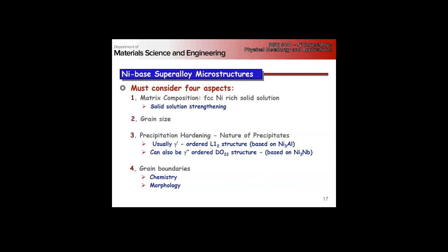When designing our superalloys, we have to think of a couple different things. Our gamma composition, because we still want to take advantage of solid solution strengthening in the gamma phase - we can get a significant bonus out of there. Grain size, of course, is something we've talked about all semester. Precipitation hardening, the gamma prime - we'll talk a bit about gamma double prime, which is a different structure that some superalloys are strengthened by. But we also need to think about grain boundary chemistry and morphology.